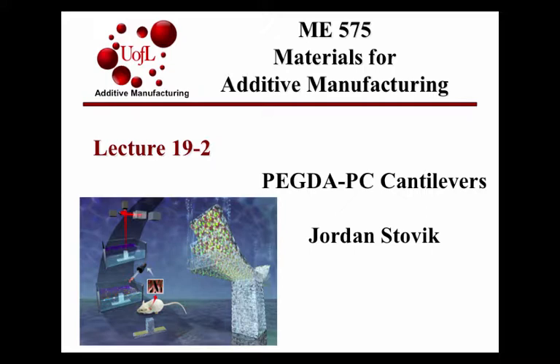So one of the things that they were looking into is that past studies had used stiffer material like silicon to create the base synthetic structure, and because of the high elastic modulus of that structure, the beating was not regular. It was very low frequency and not very effective. So they were trying to use these hydrogels that have a lower elastic modulus, about 20 kilopascals, and they thought it would allow for a better contraction and more displacement, basically.